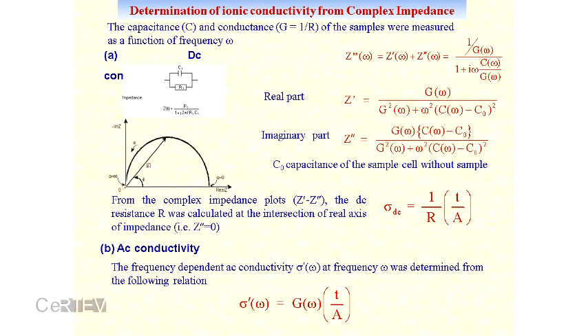in every equipment, we measure these quantities, capacitance and conductance. Then we can measure the impedance, a complex quantity, using equivalent circuits. For a simple circuit, this is the capacitance and this is the resistance or conductance in parallel. If the circuit is parallel, then we can express the complex impedance like this. Sorry, there is a mistake. There will be an i here. And the real part and imaginary part can be separated like this. You can see one extra term, C minus C0. C is the capacitance, G is the conductance, and C0 is the capacitance of the cell. Because if there is no material in the cell, there will be some residual capacitance.